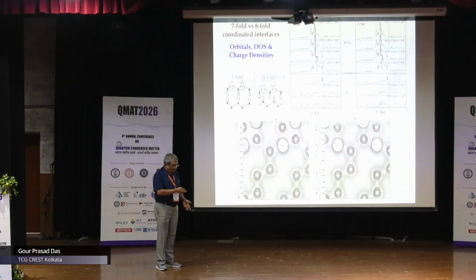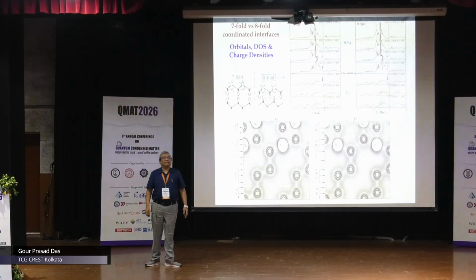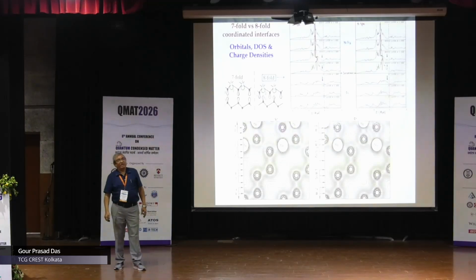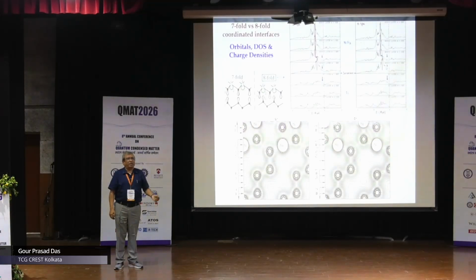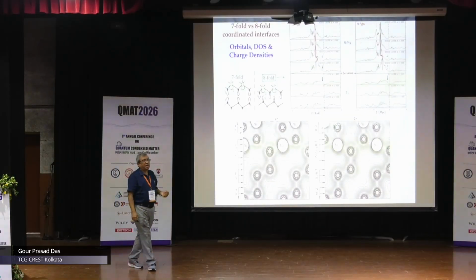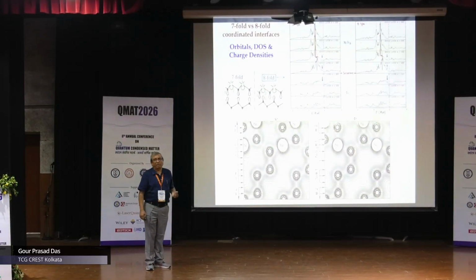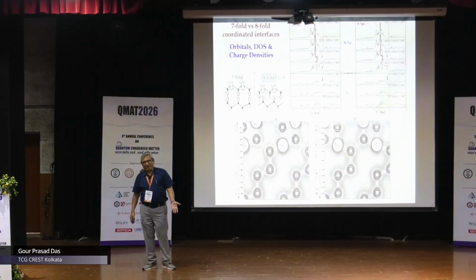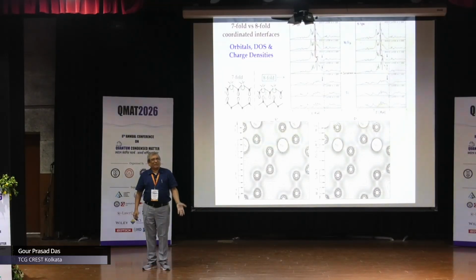Why am I showing this? Interestingly, we find that the Schottky barrier height for these two changes by as much as 0.15 electron volt. It's a huge number. For a device physicist, 0.15 electron volt is a huge number. And nobody could understand why. Because we are not changing the semiconductor, we are not changing the metal. So the metal is same, semiconductor is same, only the orientation is different, and we are getting a change in the Schottky barrier height.